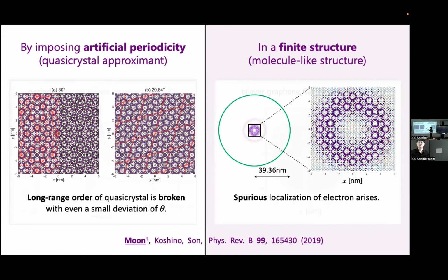For example, if you apply artificial non-physical periodicity, so this is the actual wave function, and this is the wave function of a periodic approximant. You can see local configurations are the same, but it gives periodicity and loses the long-range order of the quasicrystal. And the finite structure also gives a wave function similar to the actual wave function, but it turns out that it gives a spurious localized state at the boundary.